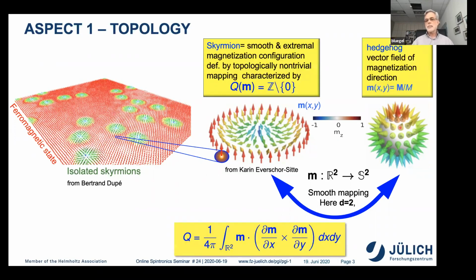And basically, the number of times you can cover the sphere by this magnetic structure is a topological number. We also call it the topological charge. It can be calculated by knowing the magnetization field. So the skyrmion is a smooth and extended magnetization configuration. It is topologically non-trivial, as opposed to the ferromagnetic state. Going from the topologically non-trivial to the trivial state, you require a non-smooth transformation. Every transformation which is smooth leaves you in your subspace of classification. If you want to move across, you have to go over a singularity.